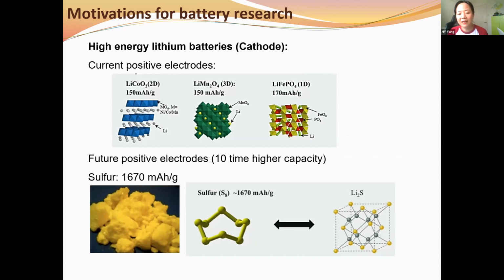Sulfur has this theoretical capacity of 1,670 milliampere hour per gram, which is 10 times higher than the current lithium cobalt, lithium manganese, lithium iron phosphate, or even lithium nickel cathodes.